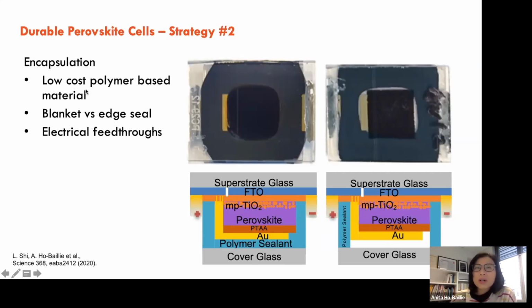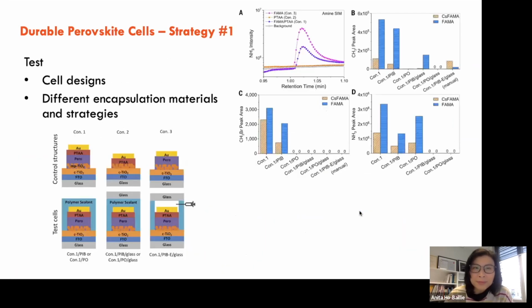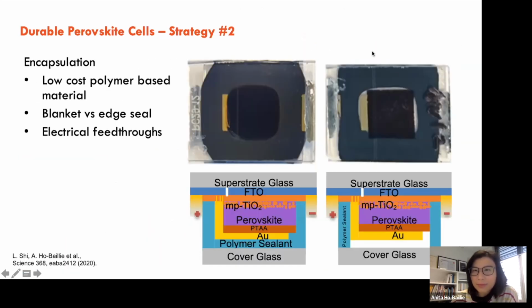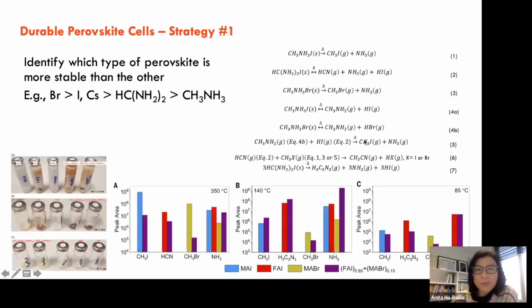In one strategy we use a low-cost polymer that covers the cells as a blanket, and in the other strategy, we just put it around the edge of the solar cell, where we use it to stick two pieces of glass together with the perovskite cell in the middle. What we found is the blanket strategy works the best, and the one where you just use the polymer to seal around the cells doesn't work as well.